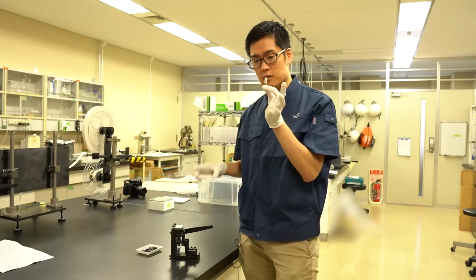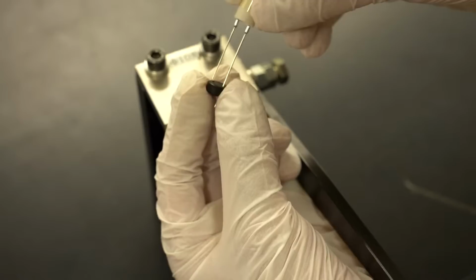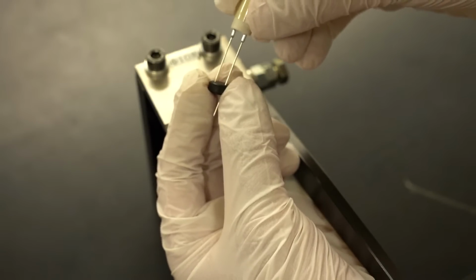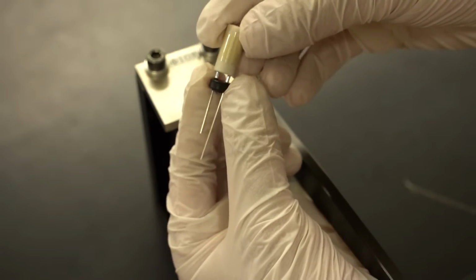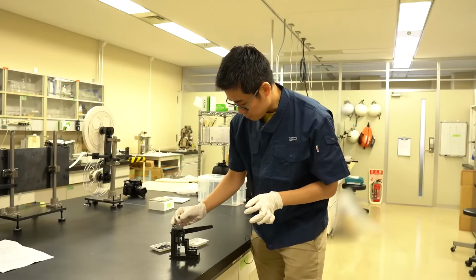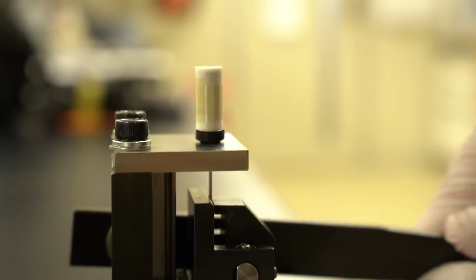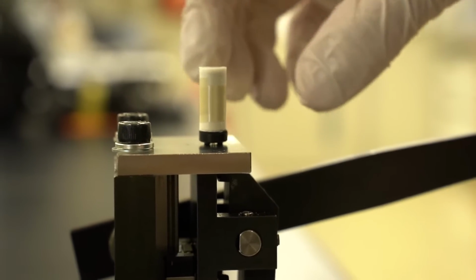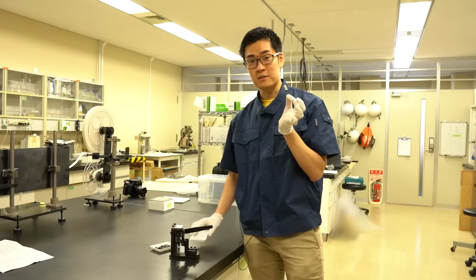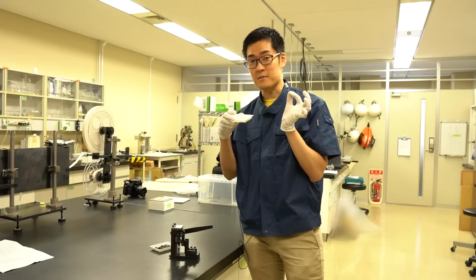I'll attach the rubber seal to the element at the lead wires. It's to seal the electrolytic capacitor. Put the wires through the holes on the seal and set the capacitor on the machine to attach the seal. This is easy. I only pulled this lever down, and the sealing is completed. All I need to do is do the same for the other capacitor elements.